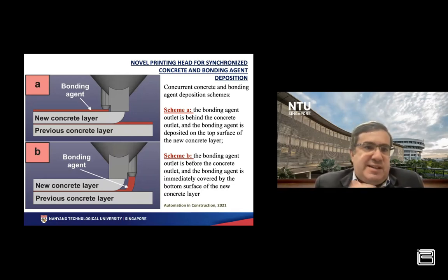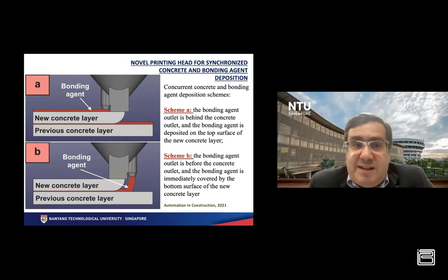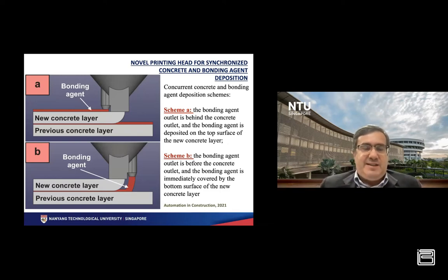In this case, because there is a time gap between printing the concrete and printing the bonding agent, depending on the cases, this may affect the bonding efficacy. In the second operation mode, the bonding agent outlet is in front of the concrete outlet. In this case, if there is an offset between the new layer and the previous layer, the bonding agent must be printed outside the part without any bonding effect.